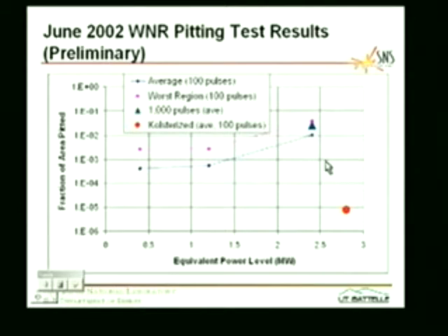The other thing is that if you take a sample and do something called Kolsterizing, which is a chemical treatment that hardens the surface, then even at very high effective power levels, the fraction of the surface that's damaged drops way, way off. So it looks like we're going to get acceptable target lifetimes. In fact, we may well wind up being limited by radiation damage rather than pitting, but in any case, the pitting is not going to drive us to have to replace this thing so frequently that we get sick of it.